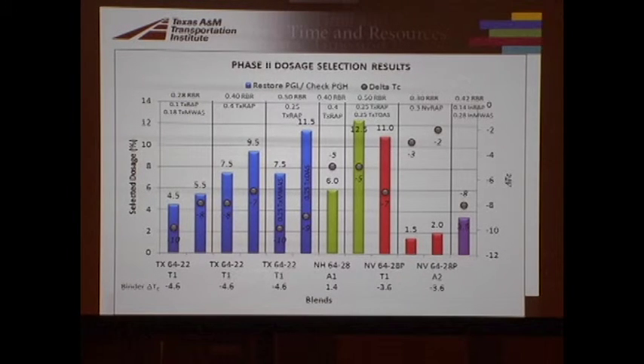Okay, so if you look at trial approach 1, this is a bunch of data, including the one I just showed you. So I just showed you this 11.5, and I just showed you this 4.5, right, with a delta TC of minus 10. I think I showed you that one. It says a delta TC of minus 9, but anyway. Okay, so what you see here is the blue values are the Texas 64 minus 22 base binder that's used in the field project, the T1. You see the delta TC of that base binder is pretty negative. It's negative 4.6. Remember, we want it to be positive.